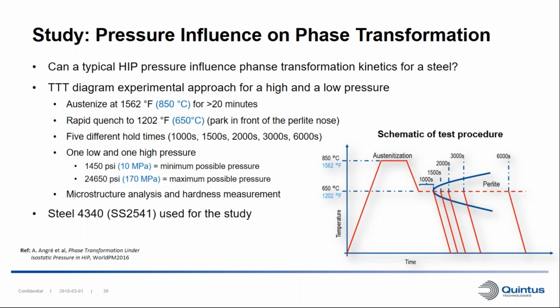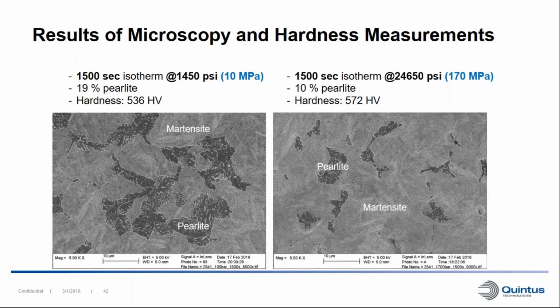In this particular study, we used a steel called 4340. And here are the results from this study. In this SEM picture, you can see that the dark fields are pearlite and the brighter fields are martensite. If we look at 1500 seconds of isothermal time at the low pressure, which was 10 megapascals, we got 19% pearlite. For the exact same thermal profile at 170 megapascals, so the much higher pressure, we only got 10% pearlite. So we could see a difference there.